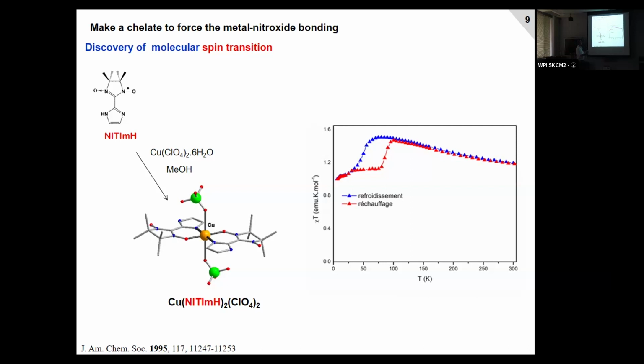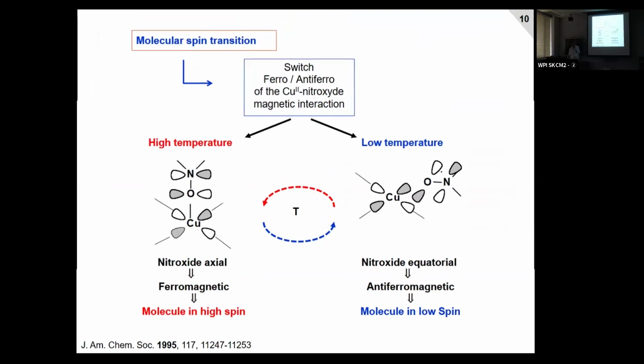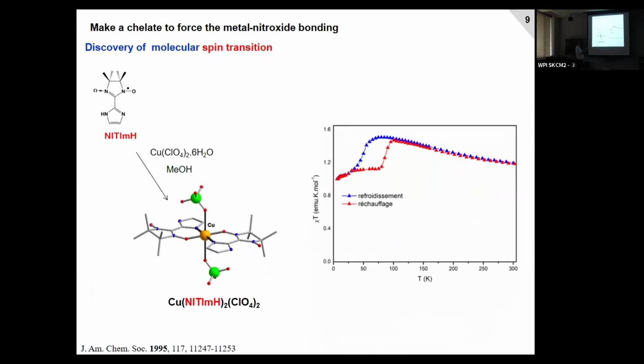Then at low temperature, you have a strong decrease of the chi-T value. And when you heat, you do not have a superposition, but you have an external loop, and you have to go almost to 60 Kelvin to reach the first. This means you have bistability. This means you have a memory system. So when you are here at 50 Kelvin, you can be in this state, or you can be in this one. Cooling or heating are not the same. So the reason why we have ferromagnetic interaction here, but when we are here, what happened?